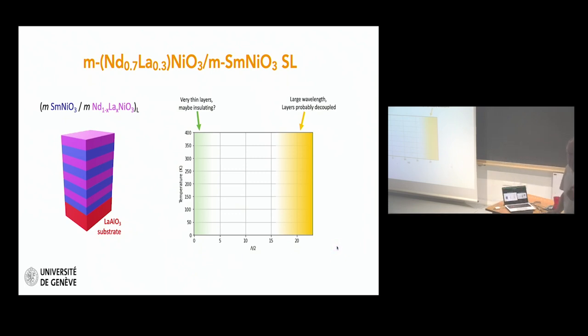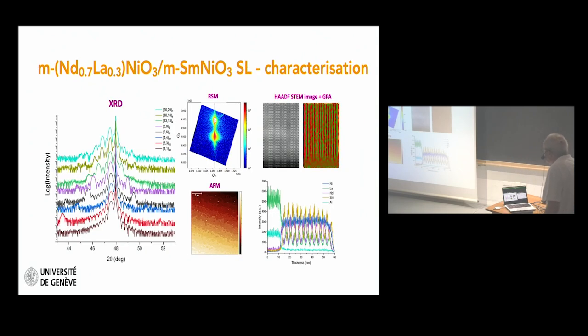Now, if you think about it, if you have thick layers, probably these layers will be decoupled, and since one of the materials is metallic, it should probably be metallic all the way down to low temperature. For the very thin layers, it's always difficult to know what will happen. So the interesting region is the middle region here, where we hope to have an insulating solid solution layer in the superlattice, but to have a metallic single layer.